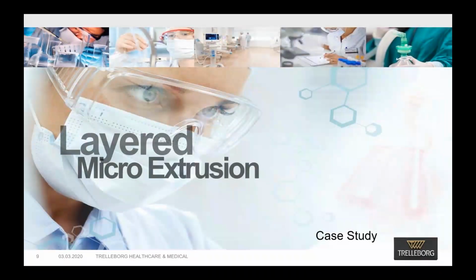So that brings us to our first case study, which is the development of a layered silicone micro extrusion. That's a mouthful. To give you some background, a layered extrusion refers to a specific type of multi-component extrusion. These can be as simple as, let's say, two co-extruded silicones consisting of a standard medical silicone, which is then combined with a radiopaque stripe, that stripe being used to locate it in an X-ray or a fluoroscope.